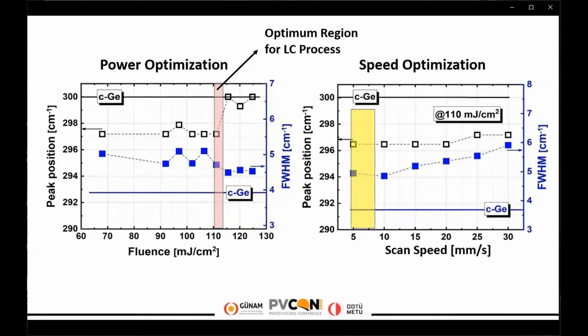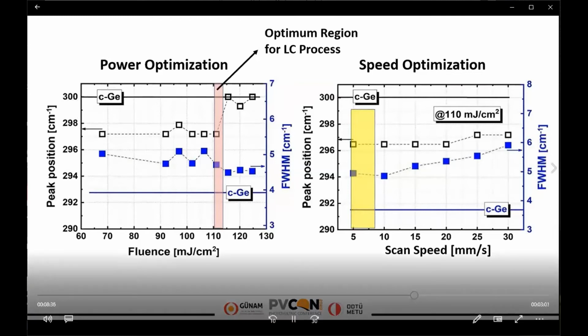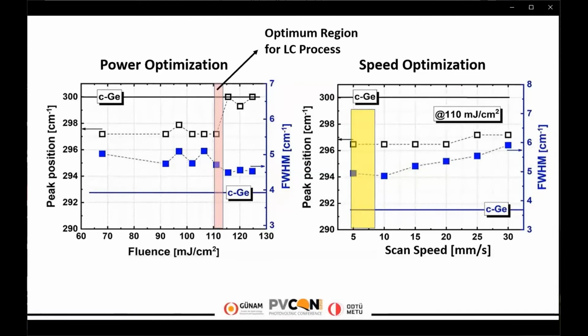There is a redshift in Raman peaks, which is attributed to the tensile stress on the film. And above the 110 millijoule per centimeter square, we observe damage on the surface. That's why we choose 110 millijoule per centimeter square laser fluence. Then the value of scan speed was changed to control the overlapping factor.